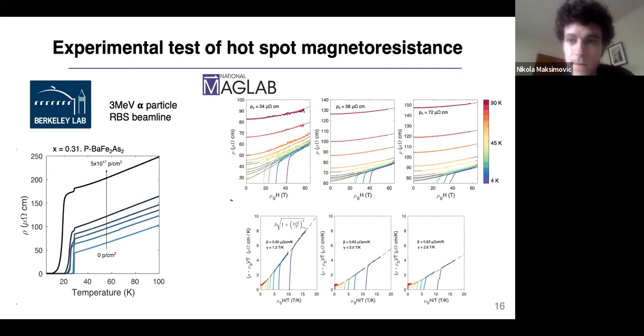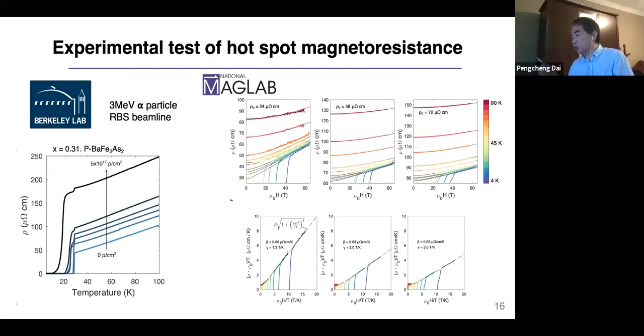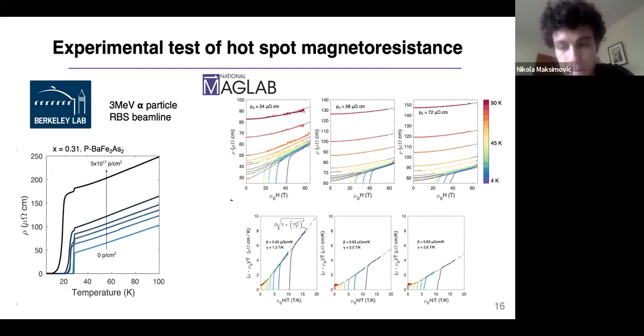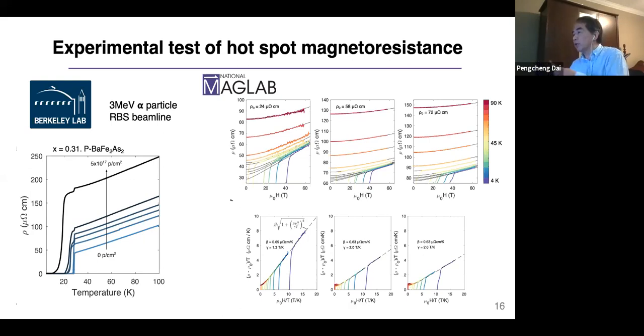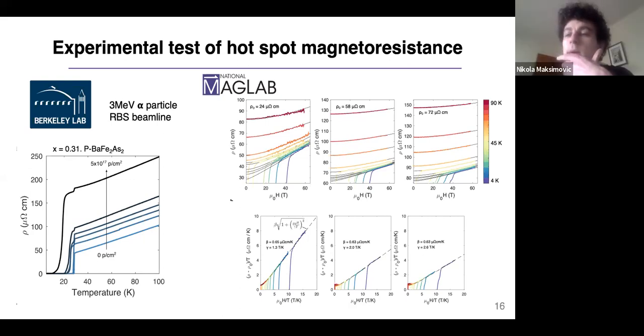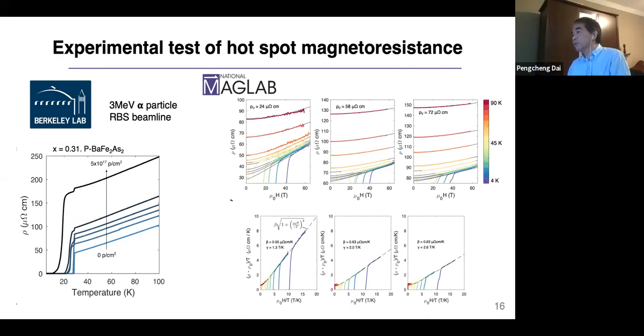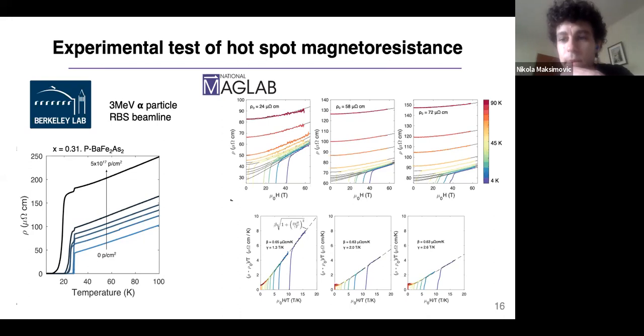In optimally doped, it's tetragonal, right? Optimal doping doesn't matter. But whether 45 degrees makes any difference, because you're arguing that this MR effect is basically opening up the gap, and that has a particular direction in real space. It does, but I think if you have tetragonal symmetry, it shouldn't. No, but if you apply 45 degrees between A and B. Yeah, I'll have to think about it. Maybe that's something to try. So your field is along the C axis, right? Field is along C in all cases. Okay. Thank you.